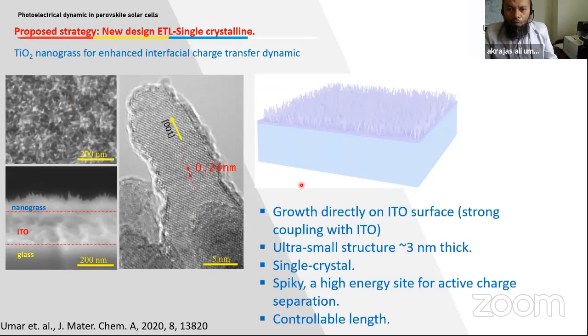Actually, the nanograss grows directly on the ITO surface, which is very strong, and we cannot remove it even with scratching with a knife or even ultrasonic. So it is very beneficial for extraction to the ITO or FTO. The unique structure is that the nanograss is a very small structure, 3 nanometers thick, and the facet is characterized by the 001 high energy facet. If we look at the individual structure, the nanograss contains a spike structure, which is a high energy site, where we expect active charge separation to occur.